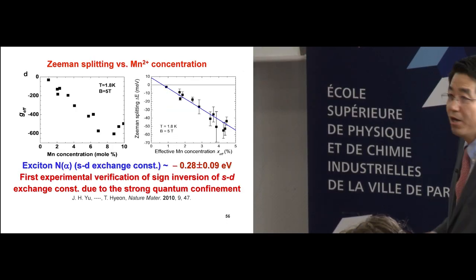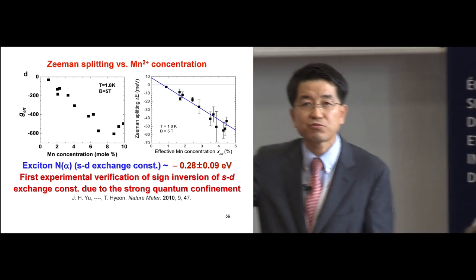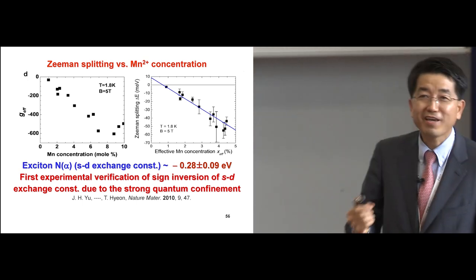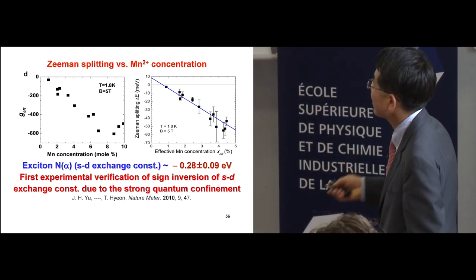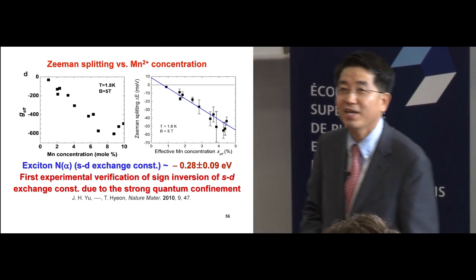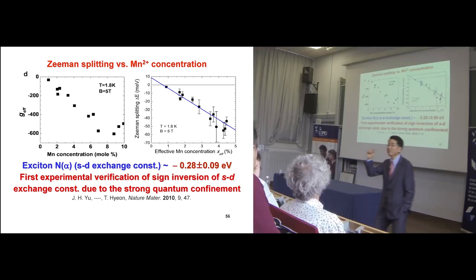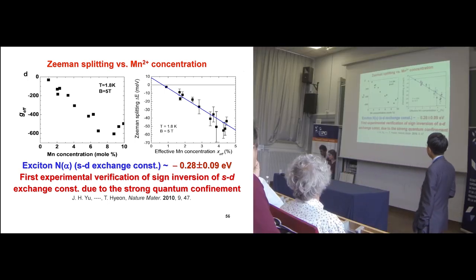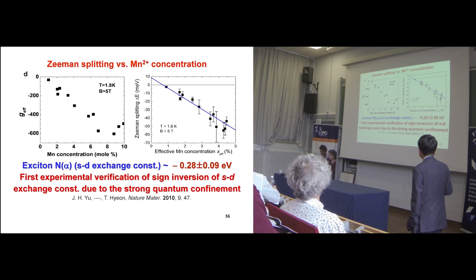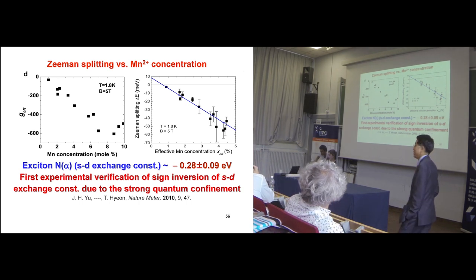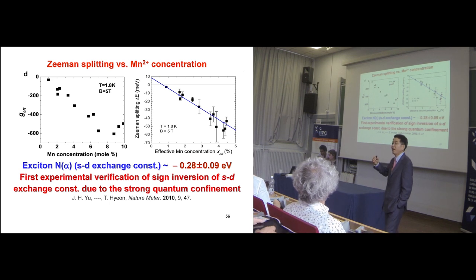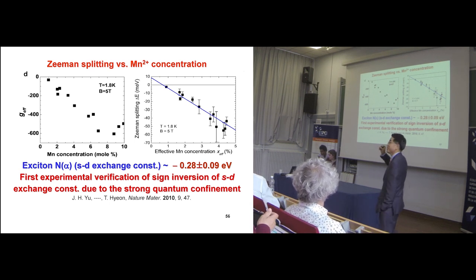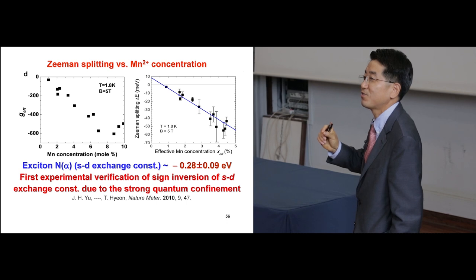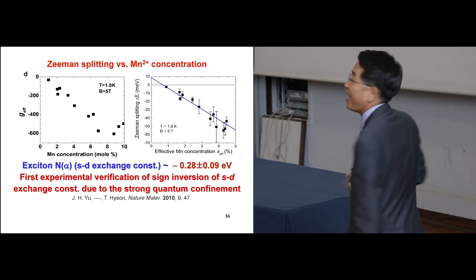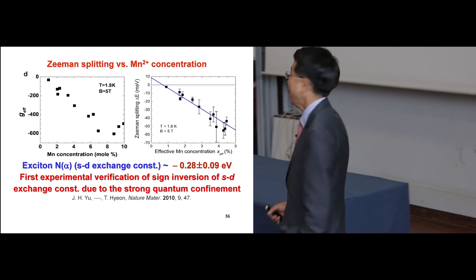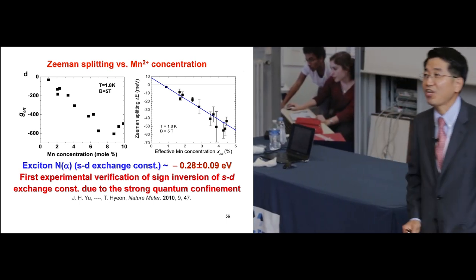On top of that, because we can control the doping concentration, we can calculate the sp-d exchange coupling constant. We can actually get this information. And for the first time, we see that theorists projected that when you make really small quantum regime structures, we might expect some kind of sign inversion of this sp-d exchange constant.